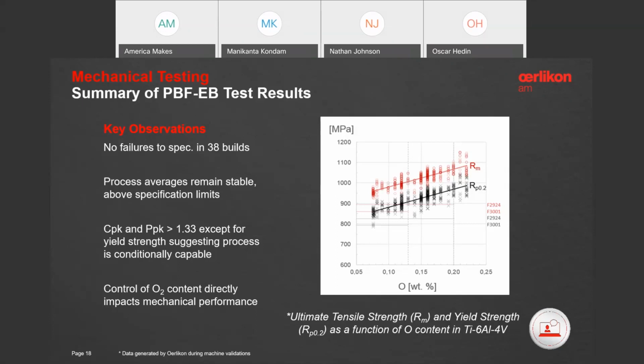One of the controls we've put in place is close monitoring of oxygen content in our powder lots. This graph shows the correlation between tensile properties and oxygen content in printed Ti-6-4, and it indicates that there's a minimum oxygen level that we need to stay above in order to meet the ASTM F2924 requirements. And this is a really important finding from this study. There's a pretty tight range of oxygen that we need to stay within to reliably meet ASTM F2924.